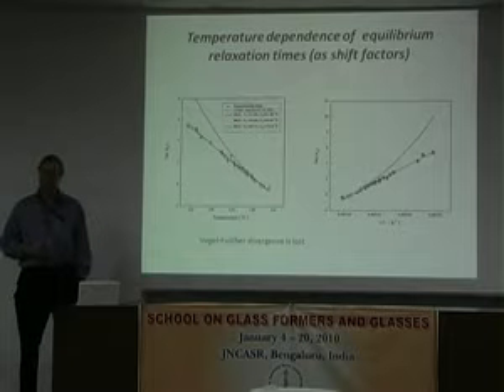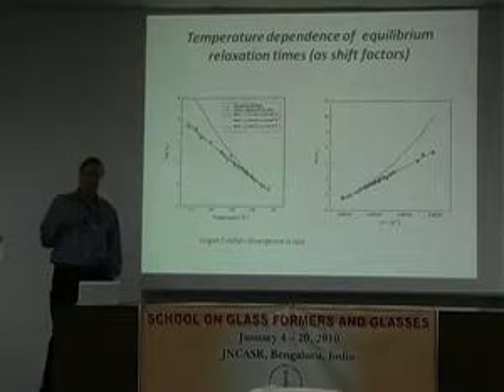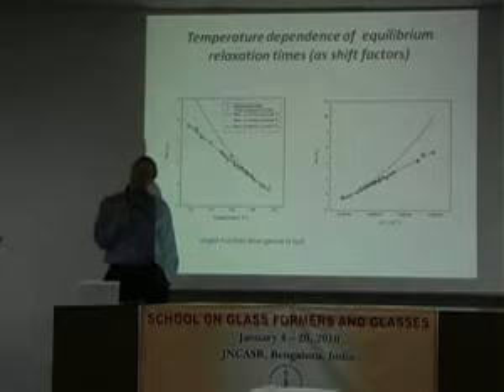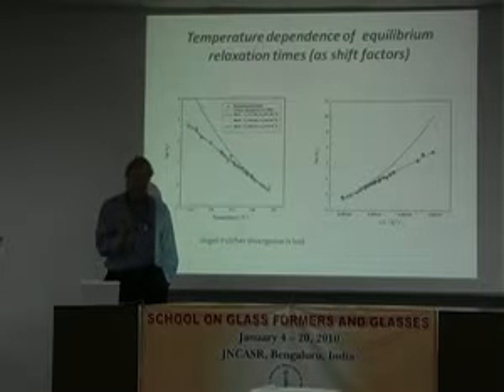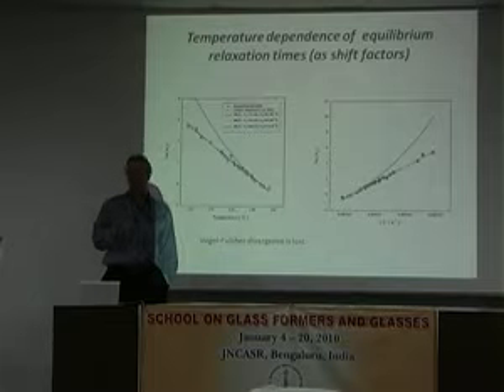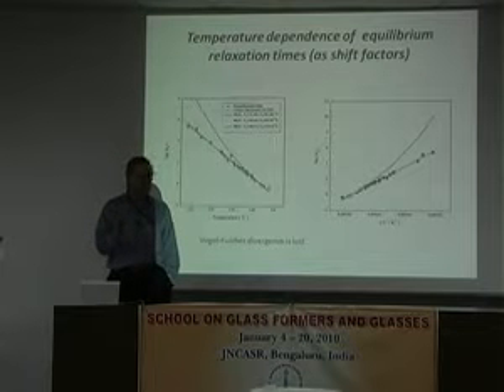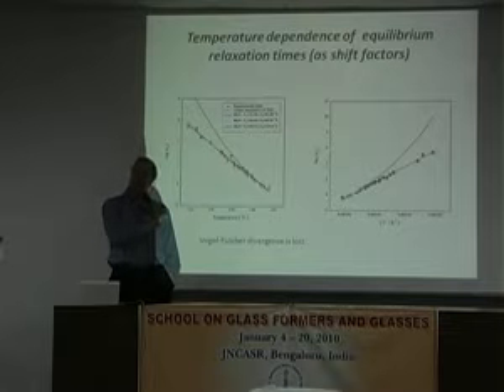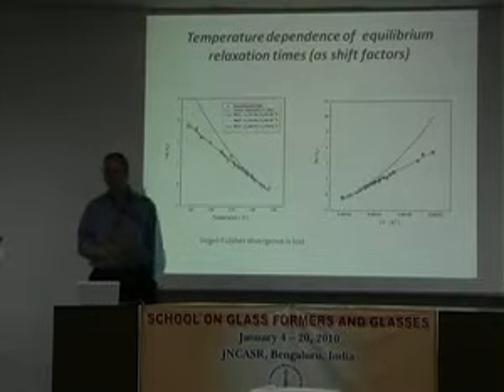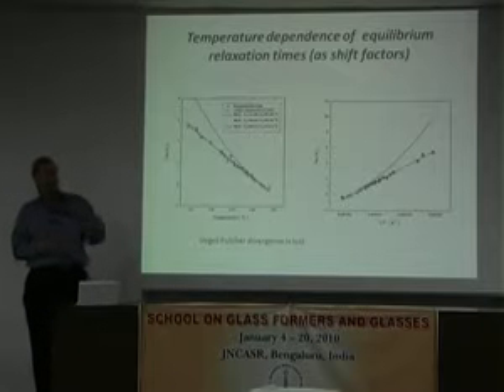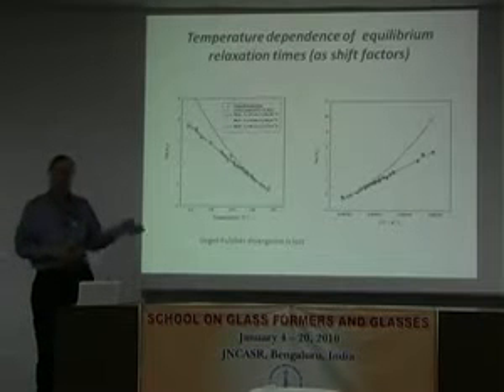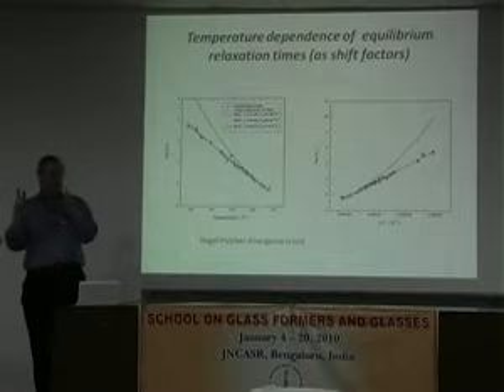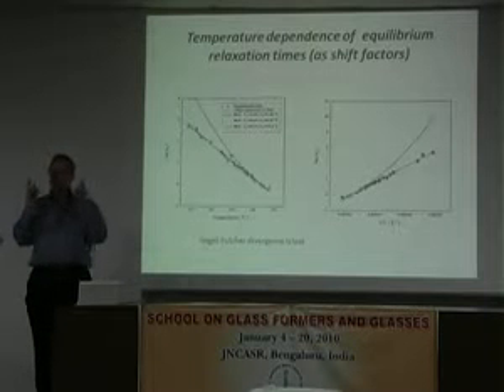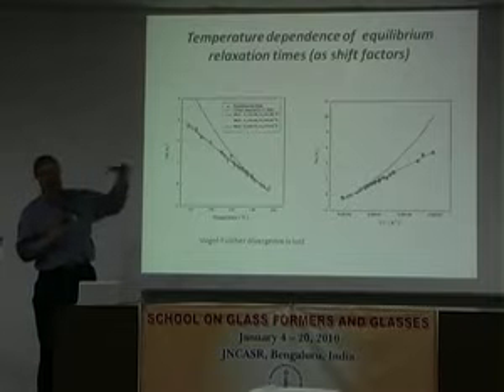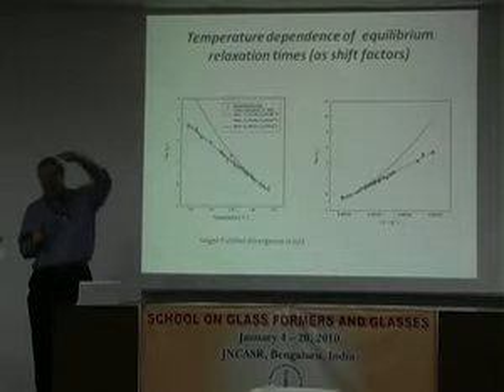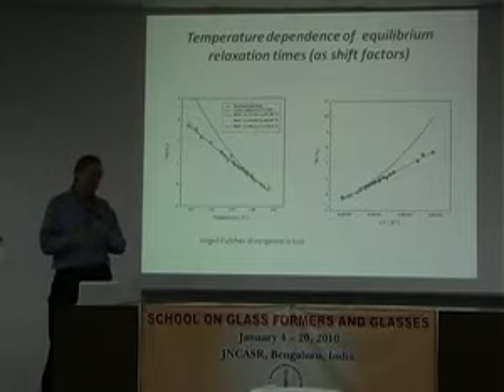Takeshi and I were talking about that over dinner the other night, and it's a true question. People seem to find in polymers, at least, and in selenium, that the mechanical response and the volumetric response seem to track reasonably well. The enthalpy response seems to have a different response time. Okay, so this goes back to that question: am I really in equilibrium? All I can say is that in this experiment, I didn't do the dilatometry. All I know is that the mechanical response has achieved a constant value, which I have interpreted as equilibrium.